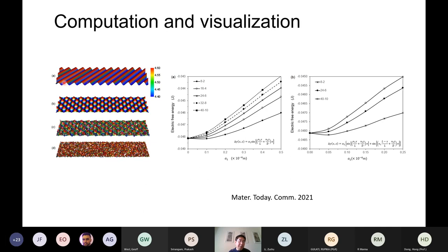And then very recently, with Zhu Shu and several other companies, we have an EU project. What we are finding is whether we can use the electric field to change the surface roughness of the mould flux. We generate different surface roughness, then pass the electric current into it, and see how the free energy changes with the different surface geometry. If we find a certain surface roughness whose free energy is higher than others, that means the surface roughness can be changed by the electrical field.